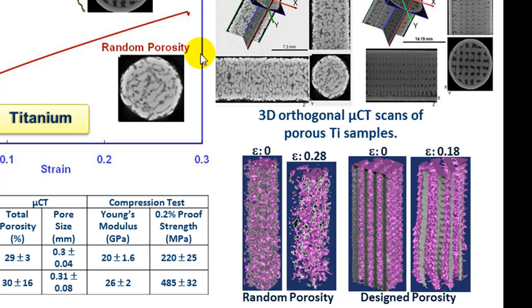Whereas here's another design porosity and pore morphology, before loading, and after loading, the structure on top and bottom are fairly similar, but the cracks are propagating more on the bottom side.